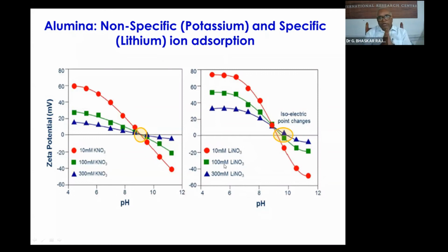So first of all, we should ascertain before measuring the zeta potentials whether a particular electrolyte, for example sodium sulfate, potassium nitrate, or sodium chloride, is interacting with our material. If they interact with our material, they are not very useful. We have to use electrolytes that are called indifferent electrolytes. That means they don't interfere with our interface. They will remain and provide the conductivity, that's all. These ions do not move or adsorb onto the surface of our particles. So we have to choose only such types of electrolytes.